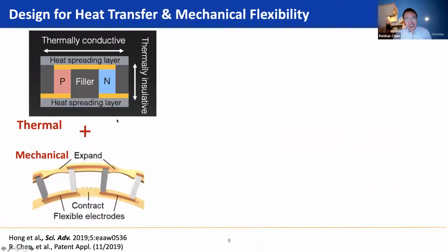And for our solution, we tried many different approaches, including flexible thermoelectric materials like polymers or organic-inorganic hybrids. But it turns out those materials still have relatively low ZT, like less than 0.2 or 0.4, so they are not efficient enough. So what we eventually came up with is what we call a flexible architecture, but with rigid materials. As you can see here, these pillars are N-type and P-type thermoelectric pillars, and they are embedded between two flexible layers, top and bottom. In our case, these layers are made of elastomers, and they are flexible and stretchable. And so even though individual pillars are rigid and not flexible, we can actually bend and somewhat stretch this device as an overall device.